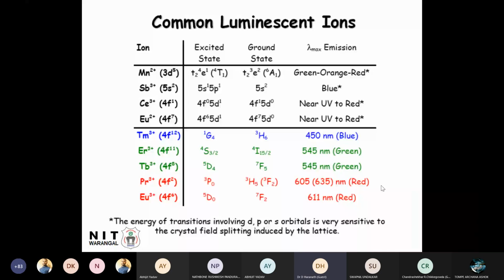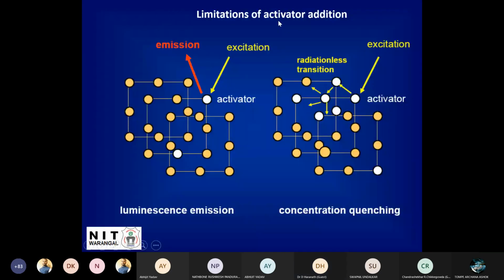And how much activator we need to put, that is another question. Like in a crystal, if you are adding an activator ion and it is substituting one of the sites, slowly if I add more and more activator, it will replace many of these sites, is it not? So how much do I have to put? See, if you put very little, then the photoluminescence emission will be a little bit weak. But if you start adding more and more activator, your spectrum will be much more intensified.